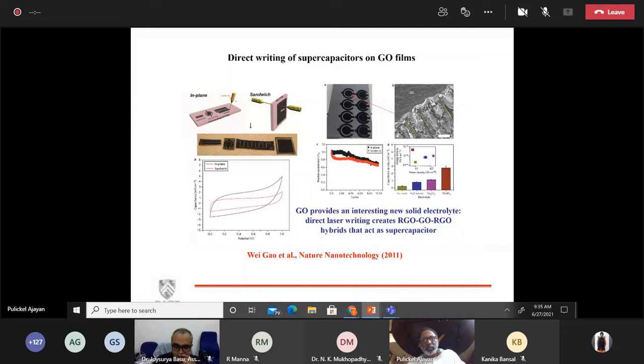This is an example of an experiment we did where we took graphene oxide, which is oxidized graphene, and then reduced it partially to reduced graphene oxide, which is more electrically conducting. And the graphene oxide being insulating and ionically conducting, one could build supercapacitor-like devices by simple laser patterning. So by understanding the chemistry of the surfaces, one can create very, very interesting devices from these types of materials.